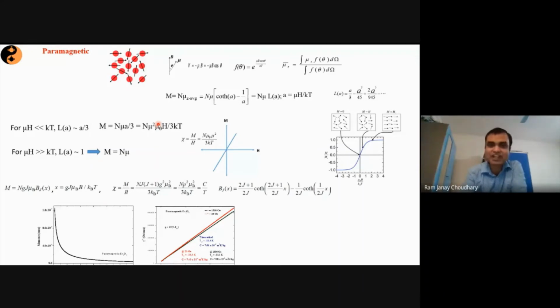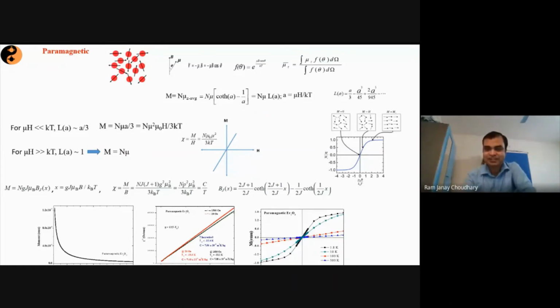Okay, I talked about this MH behavior. You see how this MH behavior looks. I've shown you 2 different regimes. See, at 300 Kelvin, which is the blue one, your MH behavior is simply straight. At 100 Kelvin, your MH behavior is still straight. At 10 Kelvin, you can see that it is straight in this particular region, but at higher magnetic field, there is some non-linearity. At 1.8 Kelvin, you can see this has a tendency of saturation, but at the lower magnetic field, this is still straight, right? So, do not always feel that in your paramagnetic material, your M versus H behavior will be a straight line behavior. This is very, very essential.